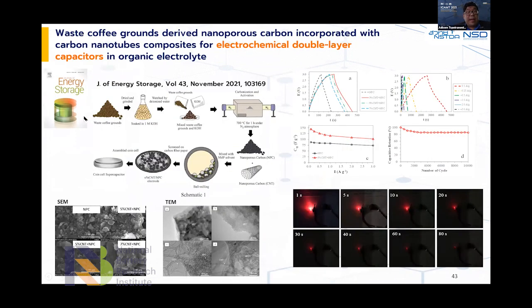Okay, and not only graphene, waste carbon such as waste coffee grounds has been used in the supercapacitor as well. So we use the waste coffee grounds, carbonize them and coat them on the surface, and demonstrate up to, let me see, more than 10,000 cycles, with capacity of more than about 100 farad per gram.